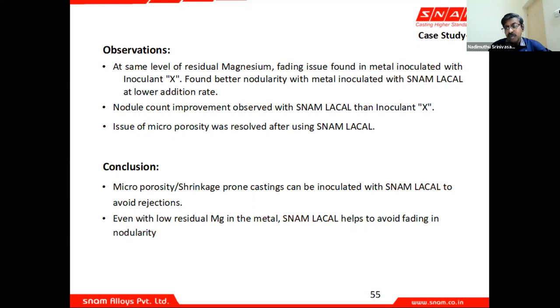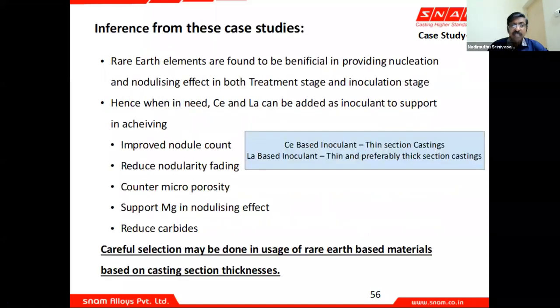If I am going to add a lanthanum-based treatment alloy, the magnesium percentage will also go up. Here, by doing this, we have only added the lanthanum in the inoculant, so the residual percentage is the same. So when I say low, it is that we are able to address the issue of the microporosity.